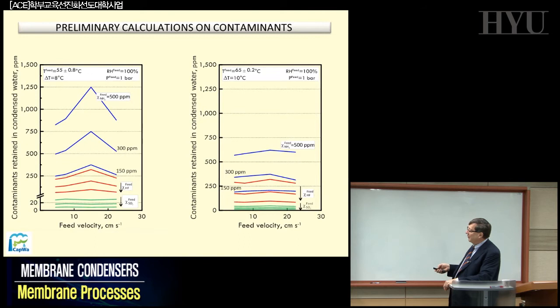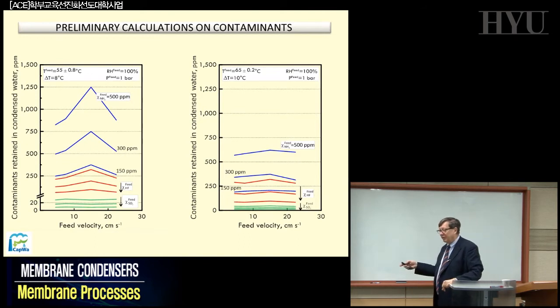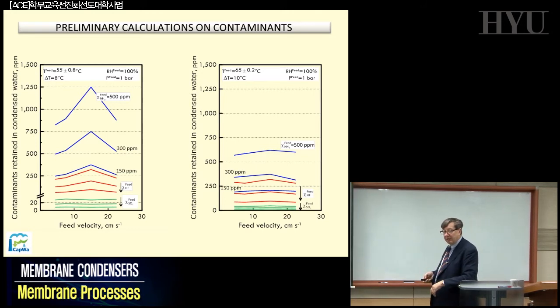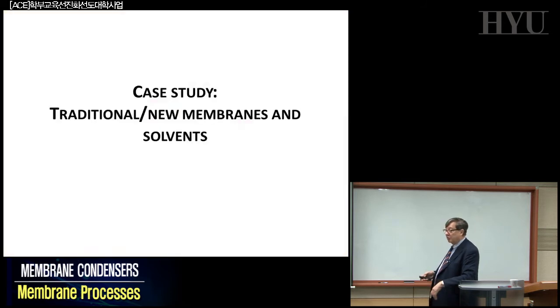If you do this kind of analysis in a more recent study, you will find literature for the SO2, which is a very important case. If you make this modeling now, these are simulations with the experimental result, you will find a very nice agreement between the expectation and the experimental result that you can obtain, in particular the one we have now with the SO2, which is one of the major contaminants that are present.